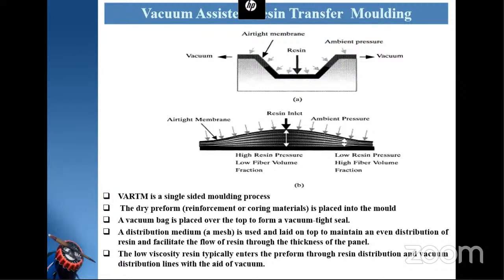So VARTM is a single sided moulding process. The dry preform reinforcement or core material is placed into the mold. A vacuum bag is placed over the top to form the vacuum tight seal. A distribution medium is laid up on top to maintain an even distribution of resin and to facilitate the flow of the resin through the reinforcement.